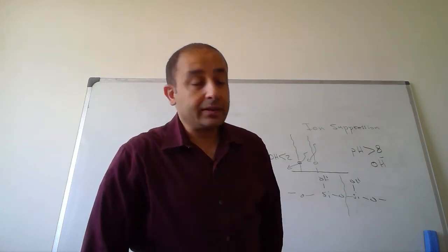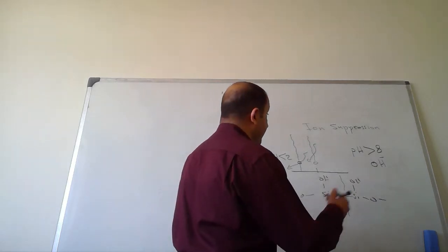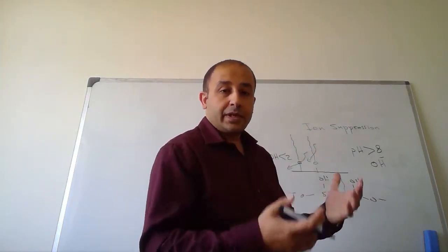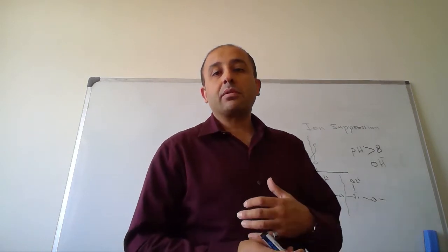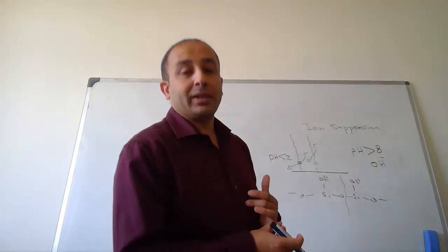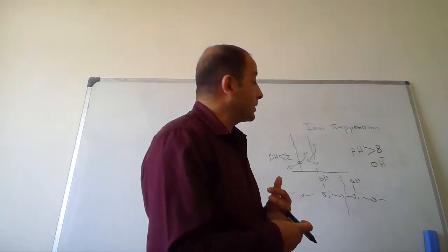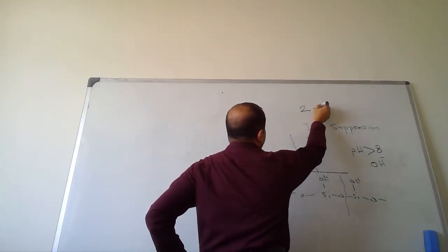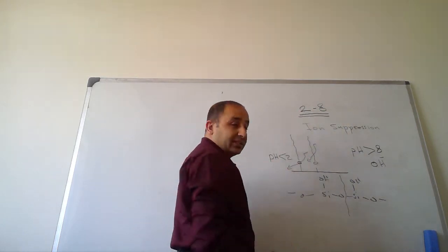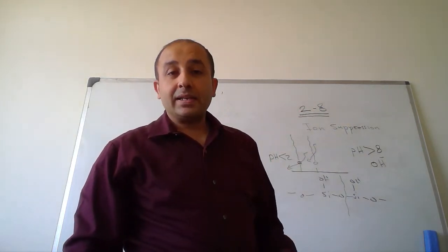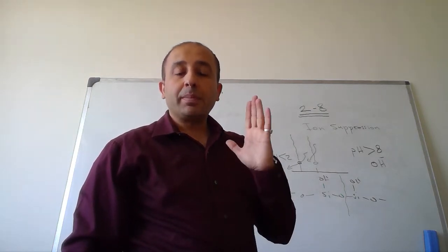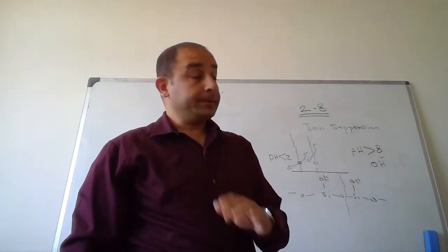So the perfect pH range of reverse phase columns, particularly silica-based reverse phase columns, which are the most dominant columns, is a pH of stability between 2 and 8. So we cannot use a mobile phase beyond this range. We have to stick with pH between 2 and 8, okay?